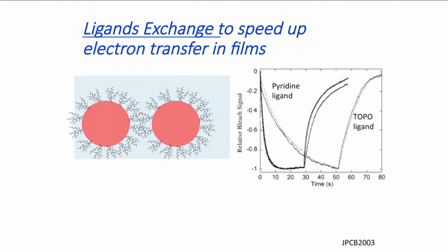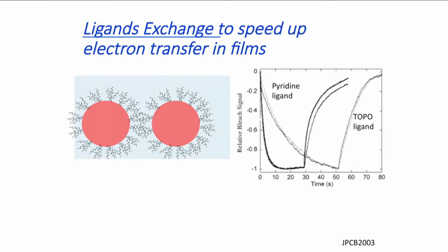We then went to a solid on an electrode inside an electrochemical cell to try to dope it. When we do that, we apply a potential. The potential is such that electrons will jump from the electrode to the particle and maybe from particle to particle, and the film is thick, so it will go through many layers of particles. But the problem was this was very slow, which means the electron was hopping very, very slowly. So slowly that it took several tens of seconds for the film to change color, which is what happened when charges are injected inside the particle.